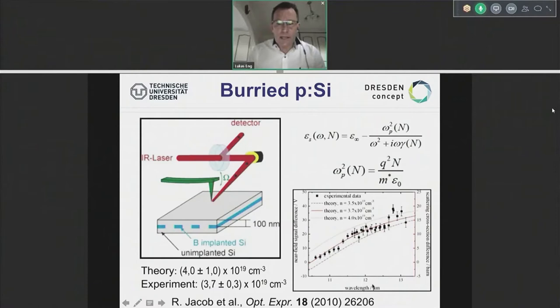In fact, this is all the data that we collected. Plugging this into a model, which is actually a plasmonic model, we find exactly the dielectric constant, which is the, let's say, macroscopic polarizability of this boron atom in here. The fit is fantastic, as you see here from these numbers. They really fit equally well between experiment and theory.